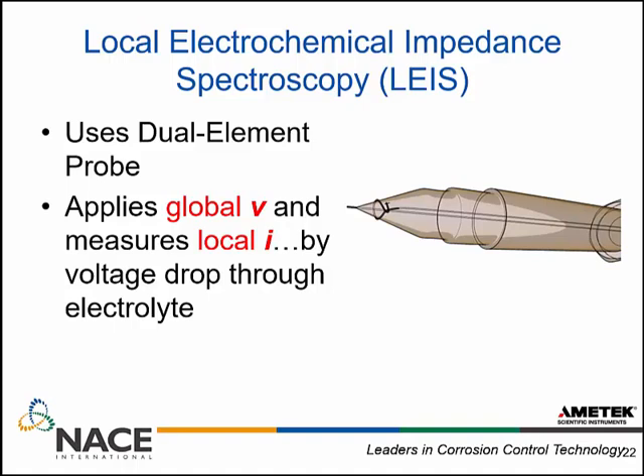Let's transition from the scanning vibrating electrode technique to localized electrochemical impedance spectroscopy, or LEIS. This uses a dual probe — I apply a voltage to my system and measure a current at the probe. I apply the same signal to the sample, and the local character of the sample determines what that signal does. Active areas are going to generate current and passive areas are not. That allows me to use the ratio between the global voltage and the local current to define a localized impedance spectroscopy experiment, which we can run at different frequencies and at different probe positions.